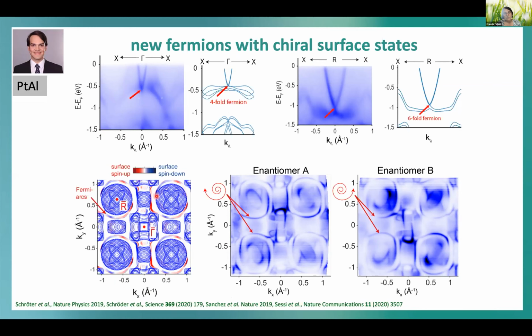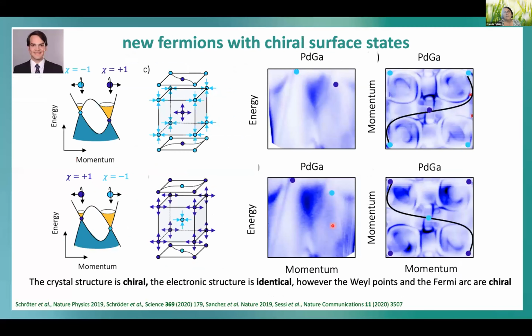Then you see this round Fermi surfaces, and around the round Fermi surfaces, you see these Fermi arcs, which are really distinguished. I hope you see the difference between the two chiralities, two enantiomers. So which means we have the same band structure, and we can say, okay, we can see the Berry phase, different sign of Berry phase here in the band structure via the chirality of the fermions.